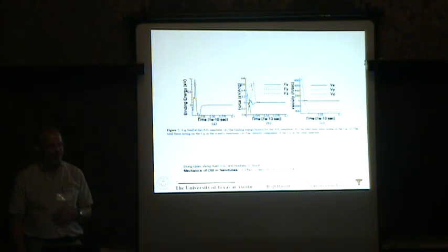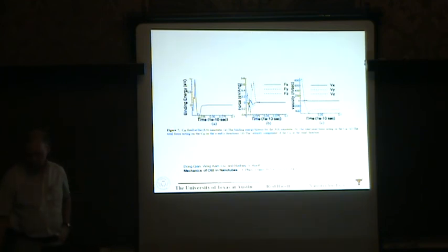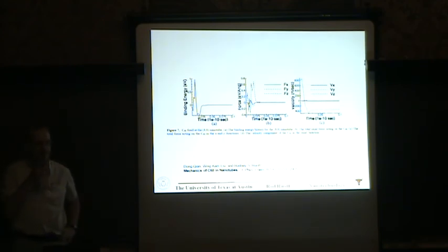Published a paper on nanomechanics results, treating something that has been observed experimentally. It is a case of a bundle, a nanotube bundle, with a collapse of a nanotube inside. It's something similar to what you... Completely collapsed or fast? Some of them are completely collapsed, but without, of course, external pressure, just due to surface tension. And this is important because if you have collapsed nanotubes, you can increase the strength, of course, against sliding failure. And I think this is because there's a much larger surface. Exactly. Yeah.